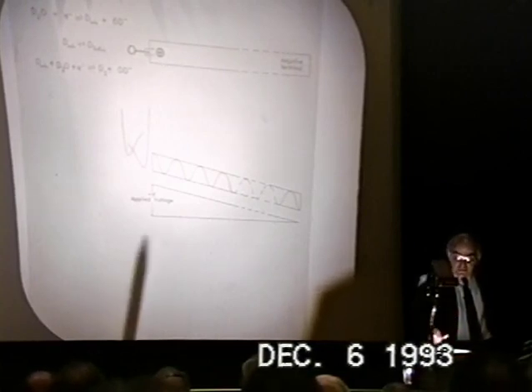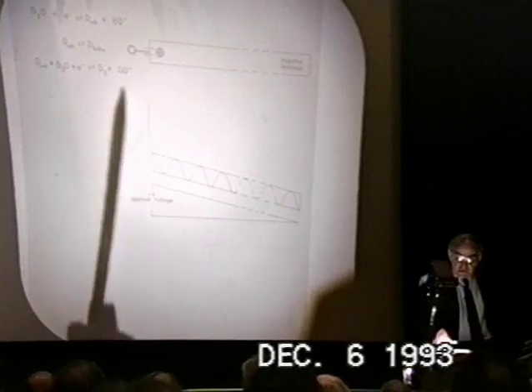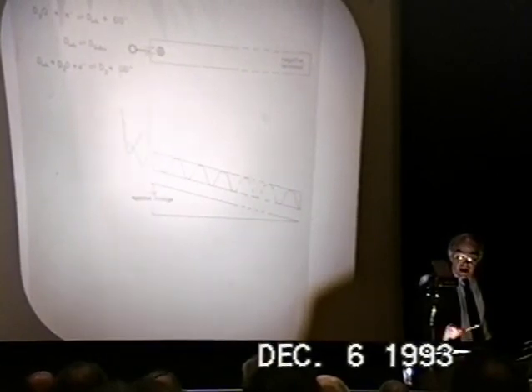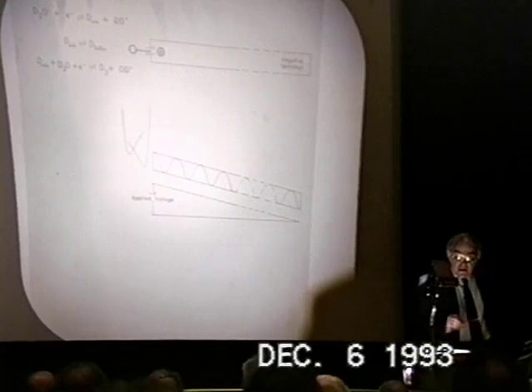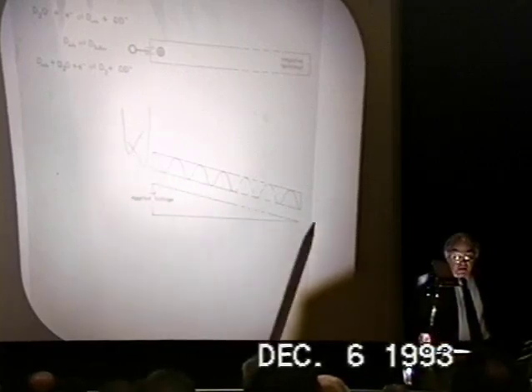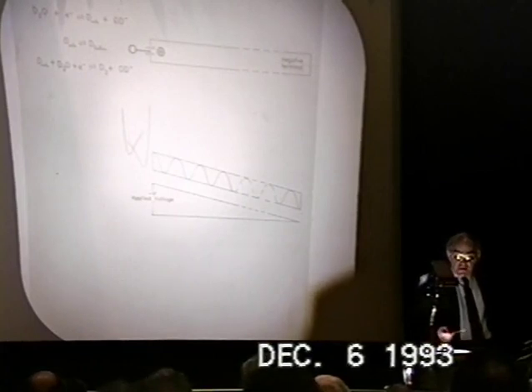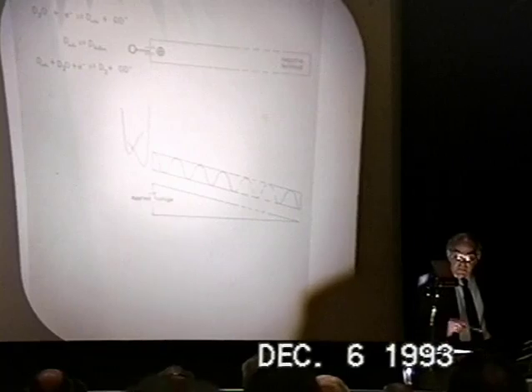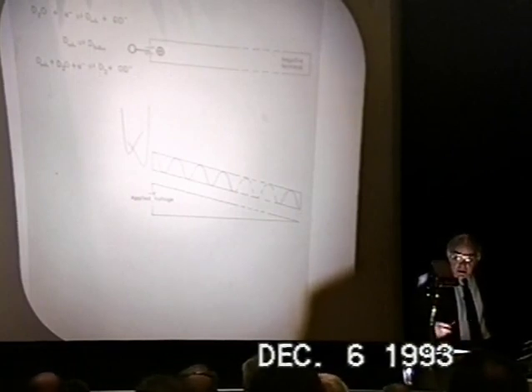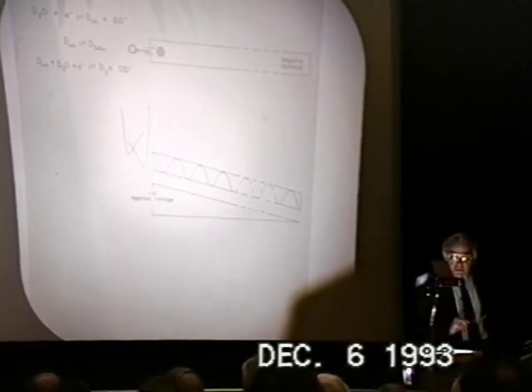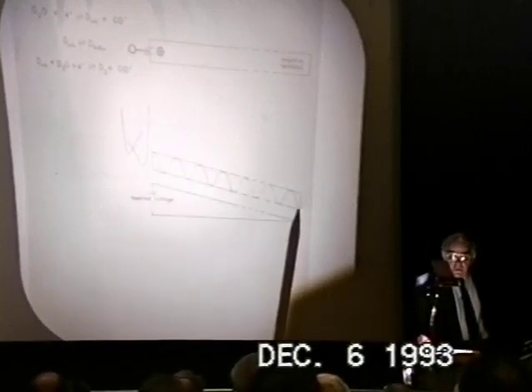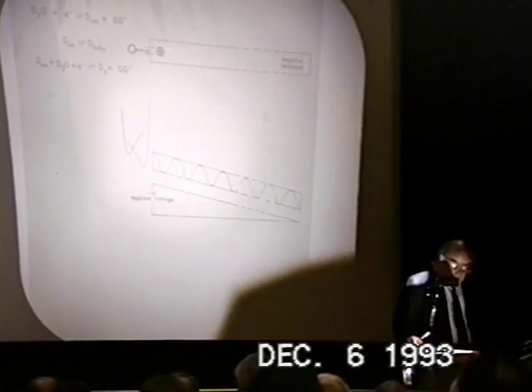What Coehn did, to summarize his experiment, was to deposit hydrogen ions into the wire, and he applied a potential difference to the wire. He found that these hydrogen ions migrate in the lattice with a velocity given by the diffusion coefficient multiplied by the Nernst-Einstein factor. That was a very significant experiment because it showed that by applying the difference in galvanic potential along the wire, you could create protons and deuterons at an extremely high chemical potential. And this is the reason which prompted us to do this experiment.